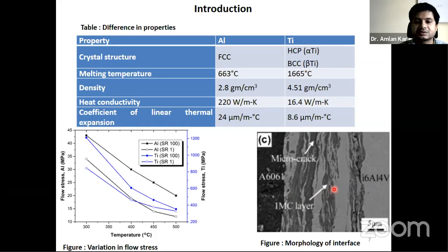And this reaction leads to the formation of intermetallic phase, because in this zone the temperature is very, very high due to the deformation. Why is the temperature very, very high? I will come to that later. But